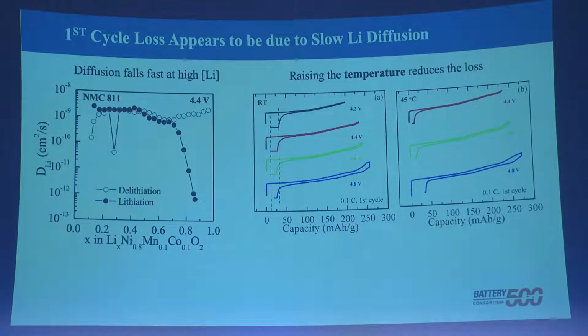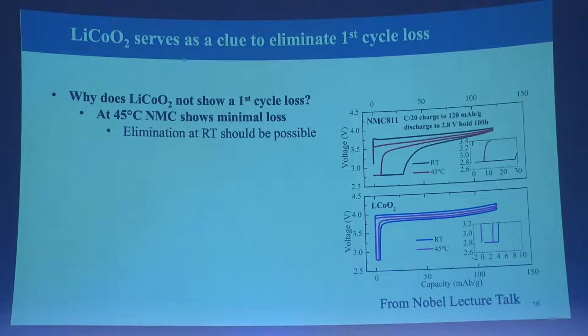So we just have to solve really a diffusion issue. Can we modify the lattice so we can go back in? And there's sufficient evidence we should be able to do that. If we look at the pure lithium cobalt oxide, there's no first cycle losses, we call it. You can see this on the right-hand side here. At the top, we have our 80% nickel, NMC.